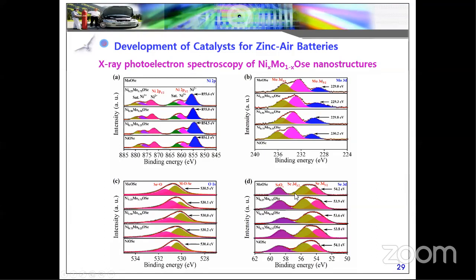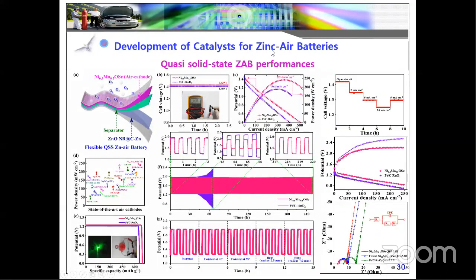In the case of selenium, you can see selenium contains two types of spin orbitals, 3d3/2 as well as 3d5/2. This is the metallic selenide phase, and this is the oxygen and selenide formation, because of selenium oxide formation. From these studies, we conclude our materials contain oxygen, selenium, and molybdenum with nickel at different ratios. So we performed these materials in zinc air batteries. I didn't discuss the three electrode systems due to time.